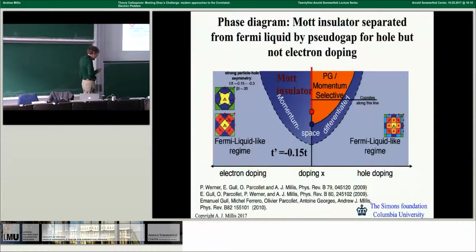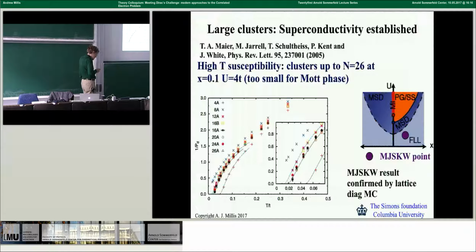All right. So you can do this. You can calculate things, right? And you can get results which are both in agreement with these other theoretical methods where you can compare them, all right, and quite consistent with experiment. And in particular, you can find out, I think now, essentially without any doubt, that in the absence of stripe phases at particular commensurabilities, the Hubbard model does have a d-wave superconducting ground state over a reasonable range of its phase diagram.